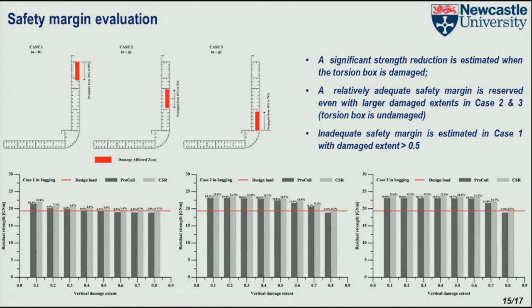Here are the residual strength index diagrams that we developed. The residual strength index is defined as the ratio between the residual ultimate strength and the intact ultimate strength. We plot all these indices as a function of the vertical damage extent. I think this could be an efficient way to make a very fast estimation of the residual ultimate strength for container ships of similar class, around 1000 TEU, under a given damage scenario, just by interpolating the results presented in all these diagrams. You may further convert these diagrams into a set of empirical regression formulas. Some people do that, but we didn't.